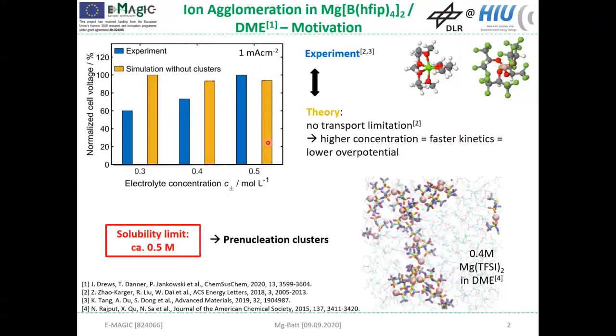It is known that magnesium salts are prone to form ion pairs or bigger clusters, and furthermore, we know that the solubility limit of this magnesium borate salt is quite low, at around 0.5 mol per liter. So with the electrolyte concentrations that are used in experiments, we are very close to the solubility limit. And therefore, it seems likely that something like pre-nucleation clusters are formed in the electrolyte, which then affects the battery performance. So that's the motivation to have a closer look at the ion agglomeration in this magnesium borate electrolyte.